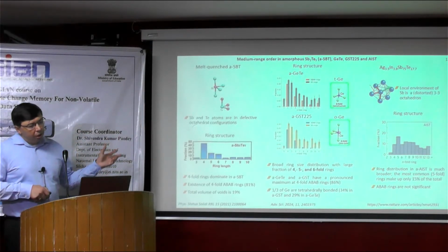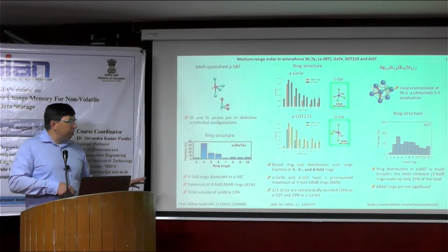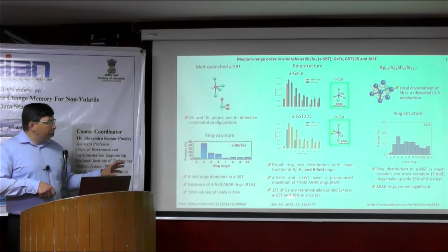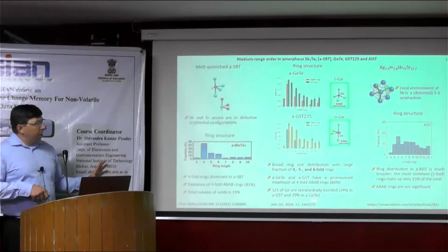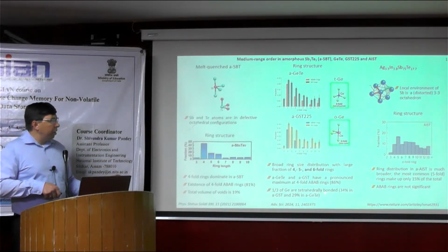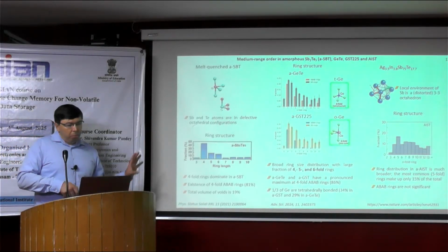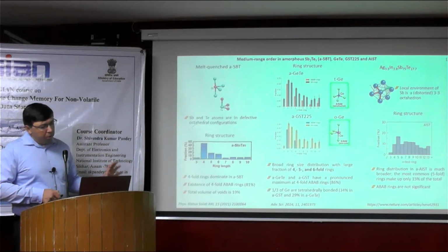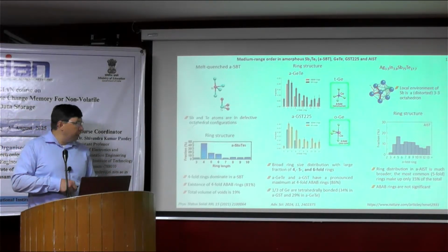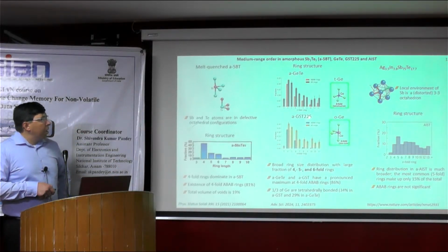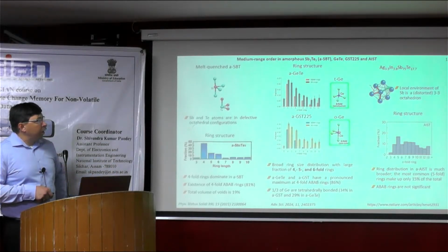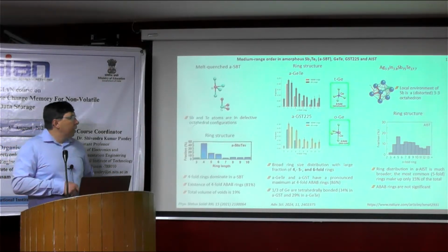So XAFS and the theoretical simulations are somehow in line, they confirm the existence of this tetrahedrally bonded germanium, but TEM does not confirm this, because of some issues, as I talked about before.